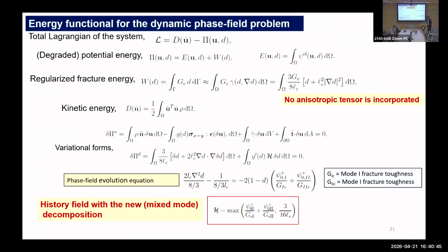Okay. So with this, we went a little more ahead. Along with quasi-static fracture simulation, we wanted to see what happens in the dynamics. So if we have high rate loading, impact loading, which is what the composite people are often very interested in, we basically implemented the system in the kinetic domain. So we have a kinetic energy term in the total energy of the system. Remember what we changed here, again, recap: we did not introduce any anisotropic tensor in the description of the phase field fracture, which was done in the previous part of my work. Okay, that was not done.